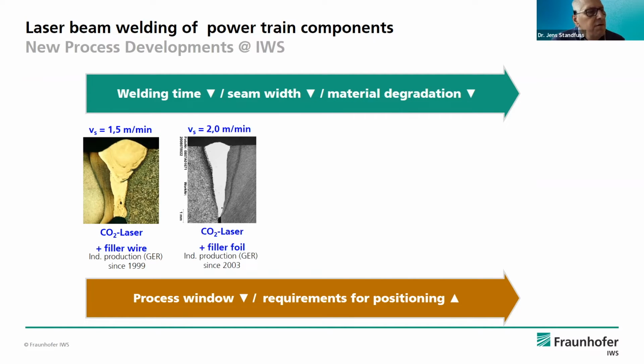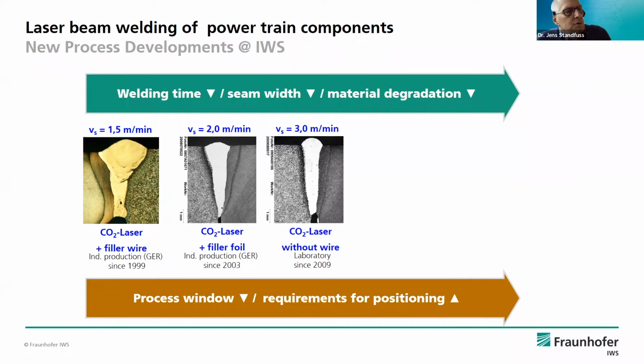So there was some development to use a foil, which has the advantage that you can increase the welding speed, and so the processing time drops down. And this was the question from the customers, why we need this filler wire. And when we speak about nickel, we have a price of nickel around 80 to 120 euro per kilogram for this filler material. This means per weld, per part, we speak about 30 to 40 euro cents only for filler material. And if we have some 100 or 1,000 parts, then it's a high amount of cost for filler wire, and so we want to speed up the welding speed to reduce the